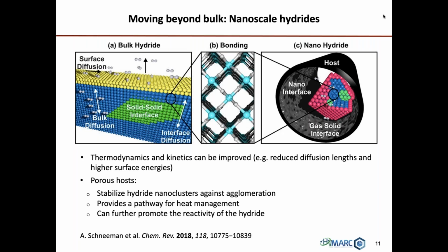So this has become a principal strategy of HyMARC to apply to metal hydrides that, for one reason or another, don't work in the bulk phase. But if you put them, for example, into a porous carbon host, something with pores, let's say, that have diameters of around 5 to 10 nanometers, you can improve both the thermodynamics and the kinetics in some cases. That's sometimes due to reduced diffusion lengths, but it also is destabilizing it because you're increasing the surface to volume ratio. And these porous hosts also serve to prevent agglomeration. They provide a pathway for heat transfer. And you can tailor the pore with different elements or groups that can further promote the reactivity of the hydride.